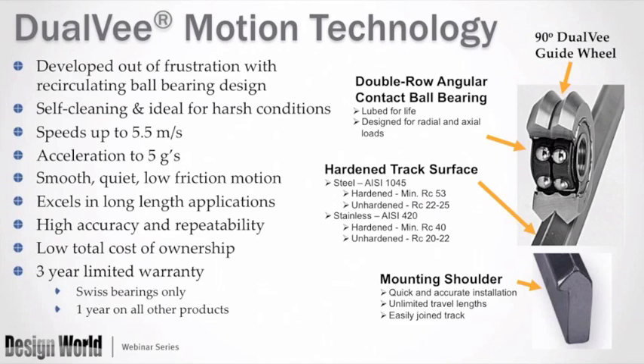So with our design here, the balls are sealed on the inside, and that keeps contaminants out. The self-cleaning design is based off of the wheel rolling on the track surface, and it can handle up to 5.5 meters per second with very high accelerations. The main application for this is in really long lengths and for high accuracy and repeatability. On our components, we have a 3-year limited warranty on our Swiss bearings and a 1-year warranty on all of our other products.